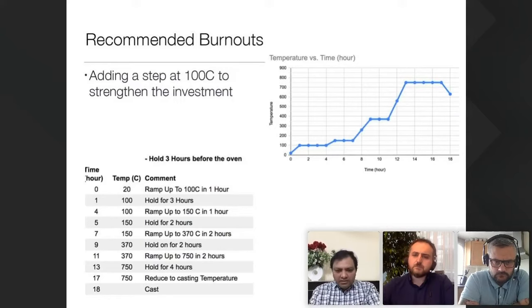Even the people doing it overnight, putting the flask in the oven, want to make sure they use the whole time. So at the best time, they use the longer duration when they close the factory - 3 hours at a certain temperature, like 80, 100 degrees, then slowly move up, making sure the moisture is completely dried, nothing left. A lot of people do this. The people doing day casting are always in a hurry, so it's a different scenario.